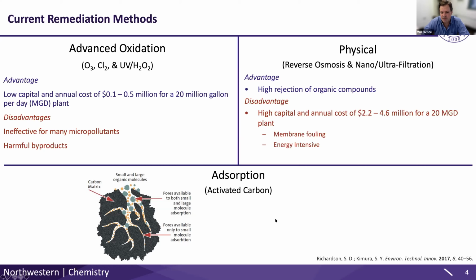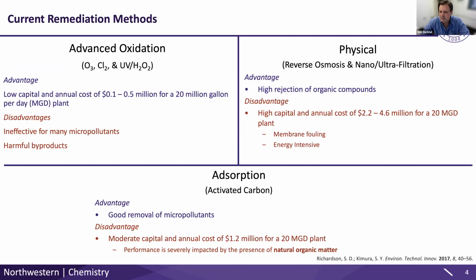And then the mechanism that we're going to talk about today is adsorption, and this is dominated especially right now by activated carbons. So essentially charred plant matter or those derived from coal. They're very high surface area materials that organic molecules tend to stick to a lot. And so these tend to be pretty good for a lot of these pollutants, but generally not excellent automatically for every single one. Moderate costs for implementing these, depending on exactly the context. And one of the Achilles heels here is that almost everything sticks to them, including a lot of naturally occurring organics that can stick to activated carbon and dramatically reduce its lifetime.